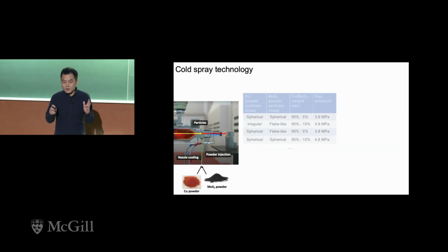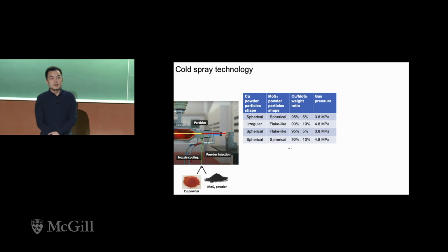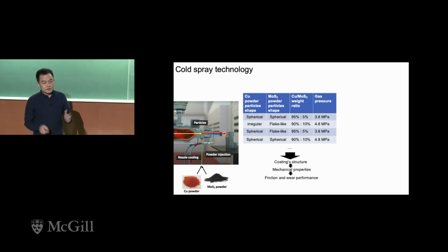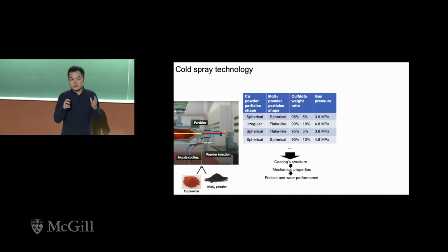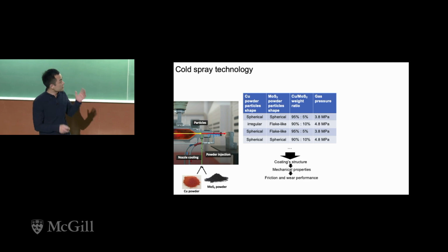The most important parameters we need to optimize include the shape and the ratio of the powders, as well as the gas pressure. All those parameters can affect the coating's structure, like MoS2 content in the coating, which will affect the coating's mechanical properties, like hardness, which will finally affect their friction and wear performance.